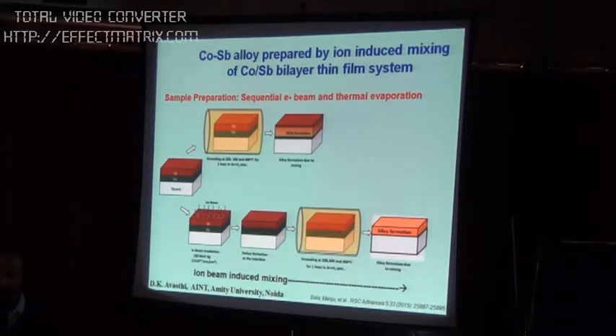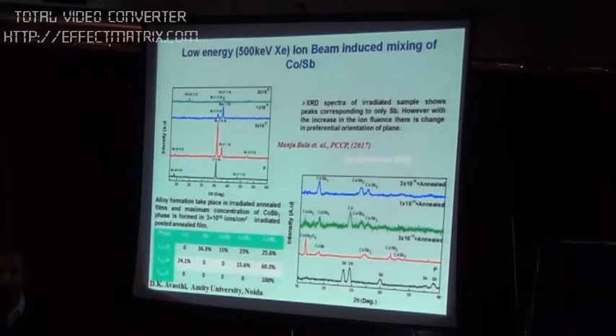And another advantage you will see in the results here, that if you have this cobalt and antimony, you can make three phases: CoSb, CoSb2, CoSb3. The best for thermoelectric is CoSb3. Okay. So here we see that with irradiation and annealing, you get the CoSb3 phase completely in this one here. So that means in certain conditions you are able to get a good quality thermoelectric thin film, CoSb3, which you wanted. So this is the ion beam processing of materials to get the desired things.